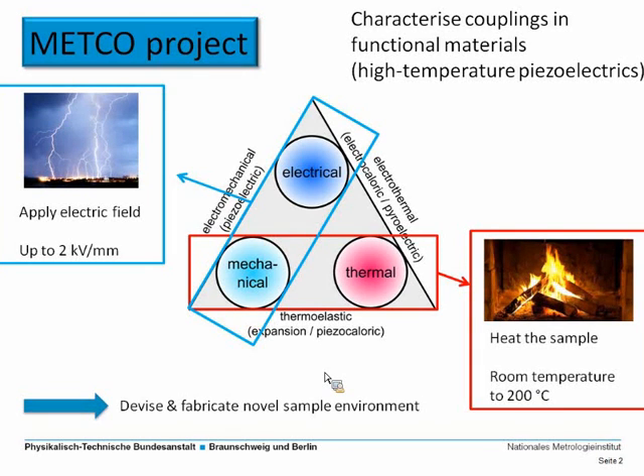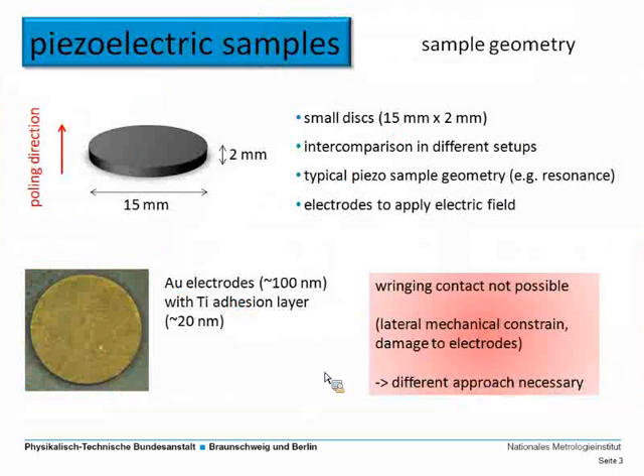But before I'm going to introduce that in detail, I'm going to talk a little bit about the piezoelectric samples we are looking at, because in some ways they differ from the samples that Guido was talking about in his talk. So instead of any kind of gauge blocks or block-like samples, we have those small discs here. They have a diameter of 15 millimeters and a thickness of 2 millimeters. The poling direction, as indicated here, is perpendicular to the circular faces, and we chose this geometry for different reasons.